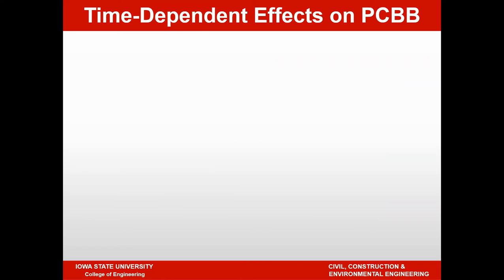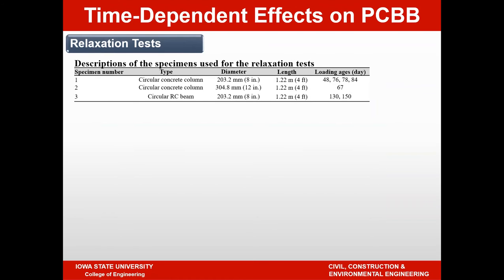Okay, so let me just start with the first test that we undertook. It was a relaxation test. We performed this test on three different members. Two are circular reinforced concrete columns. One is a circular reinforced concrete beam. The diameter of all of these members was in the 8 to 12 inch range. Specimens are 4 feet in length, and they were loaded at an age between 48 and 150 days.